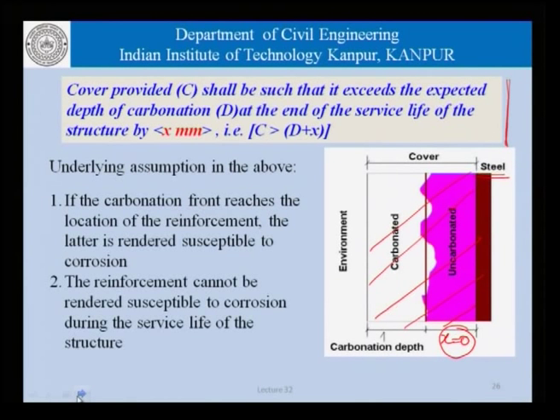In addition to that, what we are saying is that the reinforcement cannot be rendered susceptible to corrosion during the service life of the structure. So, the service life of the structure is supposed to be only till such point as the reinforcement is rendered susceptible to corrosion. Now, whether or not corrosion actually occurs is not something which we are talking about. There can be obviously situations where even if carbonation occurs, the rates of corrosion may be too low, they may be acceptable, but that part of service life is not being considered here. So, to that extent this thought process is fairly conservative.